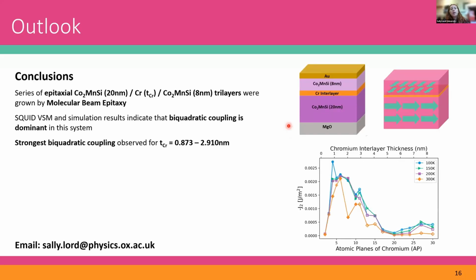So in conclusion, in this work, we fabricated a very nice set of samples of cobalt, manganese, silicon, chromium trilayers using molecular beam epitaxy. We characterized the magnetization using SQUID VSM measurements, and then extracted information about the exchange coupling behavior using simulations, but also experimental results, and found that in the system, the dominant exchange coupling mechanism is biquadratic.